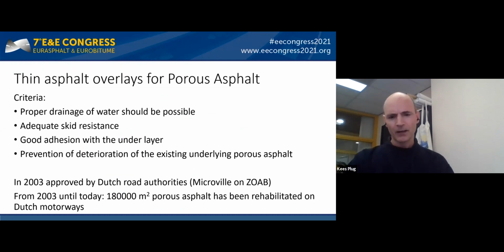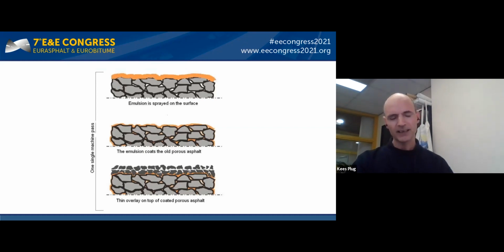Thin asphalt overlays for porous asphalt have been placed since 2003. Criteria for such a layer are: a proper drainage of water should be possible, adequate skid resistance, good adhesion with the underlayer, and prevention of deterioration of the existing underlying porous asphalt. A disadvantage, however, is that a thin overlay can only be placed on the overall road width. Applying on one road lane is not possible because of the height difference between the two lanes. As this figure shows the principle of the thin overlay, the emulsion is sprayed on the surface and the thin overlay is placed in one single machine pass with a so-called jet spray paver.